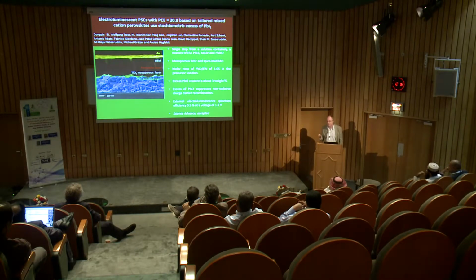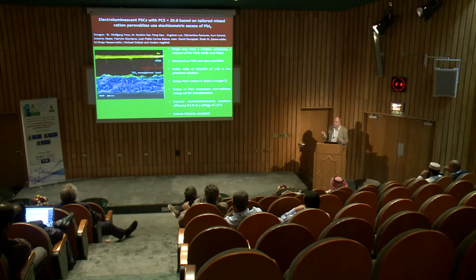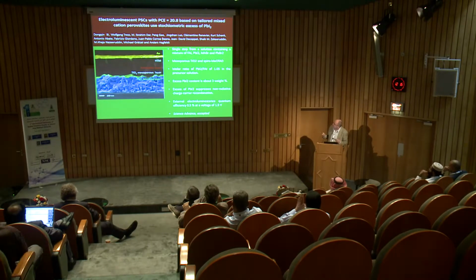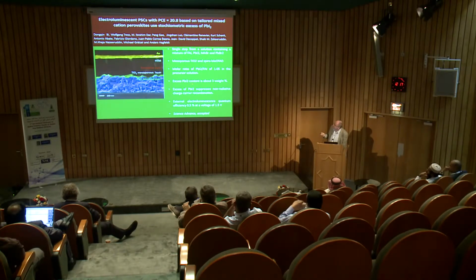That we can tell. Then in the details, where this lead iodide is in the film, if it's around grain boundaries of perovskite or at interfaces, we are not really sure where we have the lead iodide excess. And exactly where the recombination process is decreasing, we have to look further. So more questions are coming up, but we can definitely say that it's beneficial, with this excess decreasing recombination. So that's the latest news.